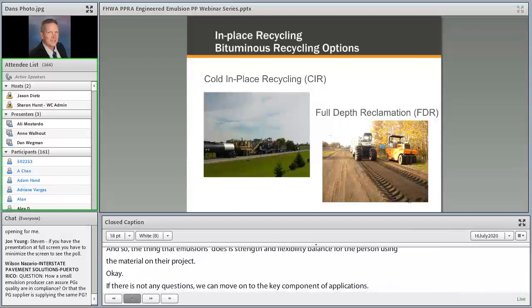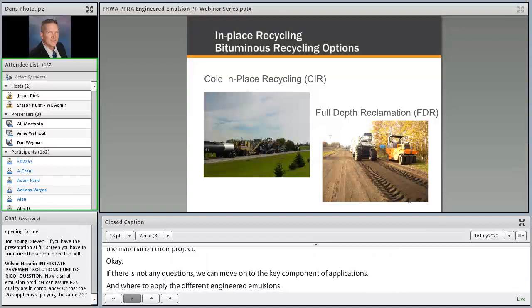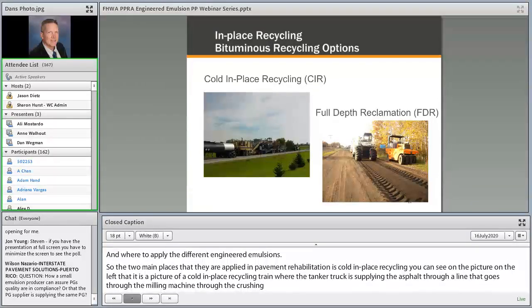The two main places that they're applied in pavement rehabilitation is cold in place recycling. You can see in the picture on the left a cold in place recycling train, where the tanker truck in front is supplying the asphalt through a line that goes past the milling machine to the crushing unit, and then gets mixed in a pug mill where the emulsion is mixed with that crushed milled material and then remixed and placed right back down on the roadway.